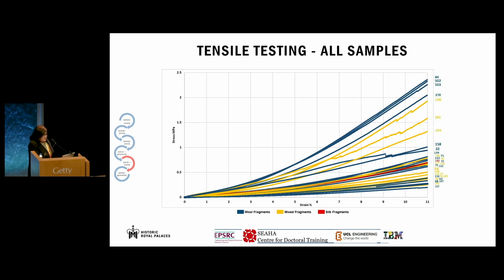And here, you can see the results of the tensile testing of the 33 historic fragments. 3 areas of each of these fragments were tested until 11% strain, and the figure shows the average of each fragment. The blue lines represent wool, the red silk, while yellow indicates mixed areas. So these stress-strain curves show that the homogeneous wool fragments were generally stiffer than the homogeneous silk fragments. And that outcome was in line with Philippa's experimental results we discussed earlier. However, for mixed or non-uniform wool fragments, the results were not as consistent, most likely due to the complex structure or presence of slits.